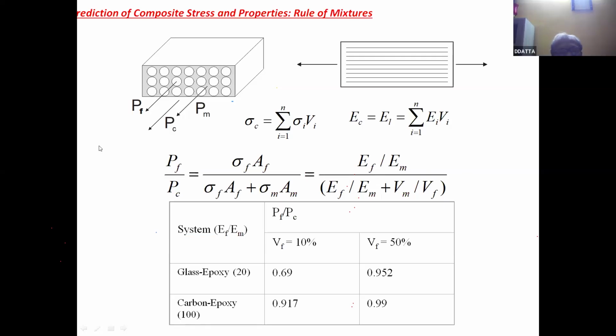Okay, fine. So here this is a load on the composite, and that is divided into fiber load and matrix load. And this is the composite stress. This can be shown to be sigma of sigma_i V_i. That means the individual constituent stress and its volume fraction, so we multiply and then add them up and get the composite stress. Similarly, we can also find the composite Young's modulus in the longitudinal direction, sigma E_i V_i, where E_i is the Young's modulus of the ith constituent and V_i is the volume fraction of the ith constituent, then the product is summed up to get the total Young's modulus of the composite.